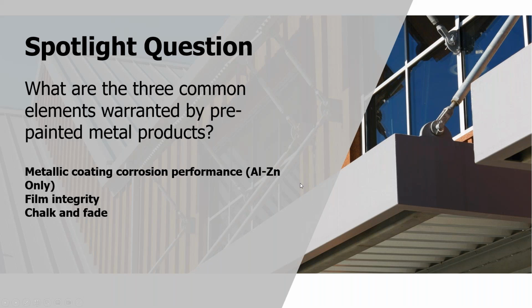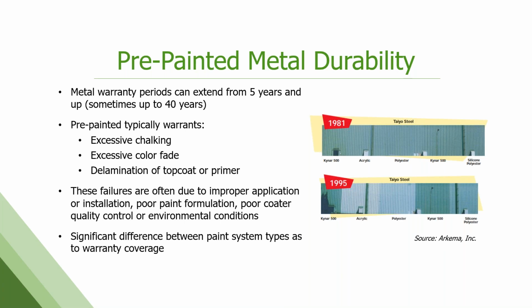You may have metallic coating, you may have some corrosion warranty that comes with your substrate, depending on what you're using. But when it comes to the paint, we're looking at film integrity, chalk, and fade. And film integrity is, does the paint stick? Does it stay on the strip long term? So again, these warranties can be anywhere from 5 years to 40 years, 45, 50 years now.